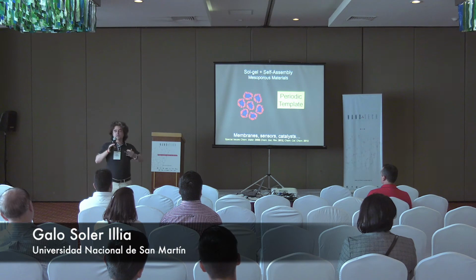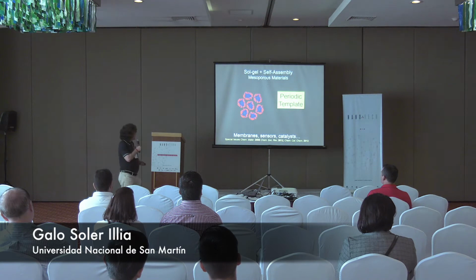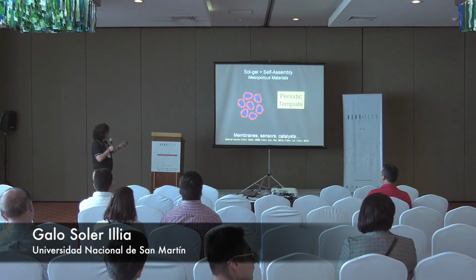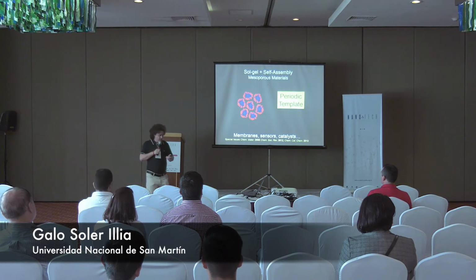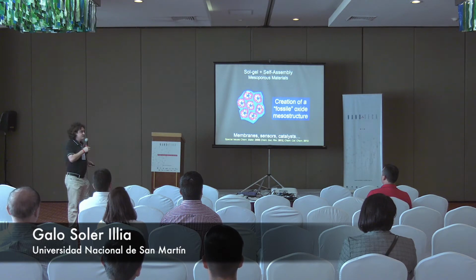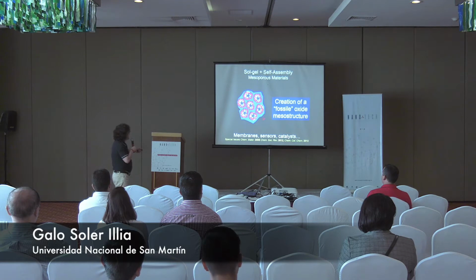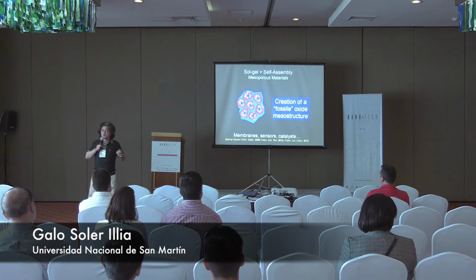You can concentrate these micelles, for example, by precipitating, by making a liquid crystal, and you part the space, and you can make sol-gel chemistry. Sol-gel chemistry is very mysterious, don't worry, it can be done, but essentially it's inorganic polymerization. And if you are able, for example, to make an inorganic or an organic polymer in the hydrophilic region of this space, you end up with this kind of fossil structure, in which you have the micelles trapped into a second phase you form. For example, you precipitate silicon dioxide there. Or you make a polymer, and then you carbonize it.